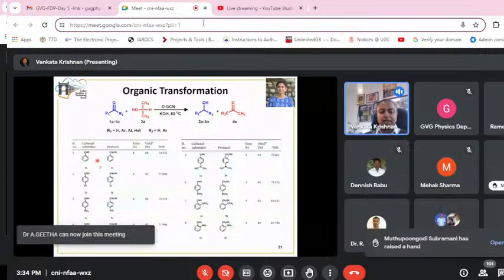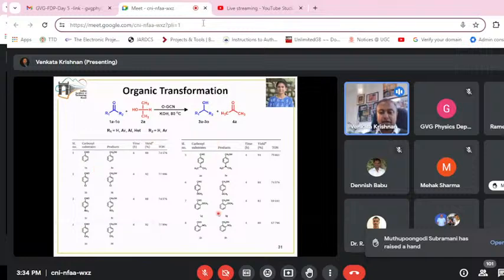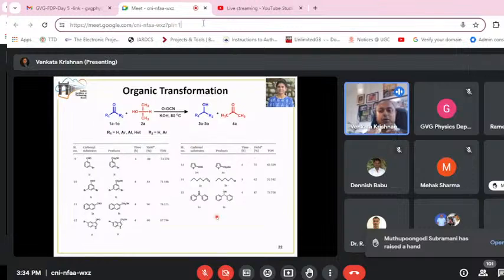We did a detailed substrate scope study wherein we changed the different carbonyl groups and did the same reaction, which indicates the universality of our catalyst and the process. We tried with electron withdrawing groups, electron donating groups, aliphatic groups, and aromatic groups. The reaction was going successfully in all the cases, which indicates the universality of our catalyst and the process.